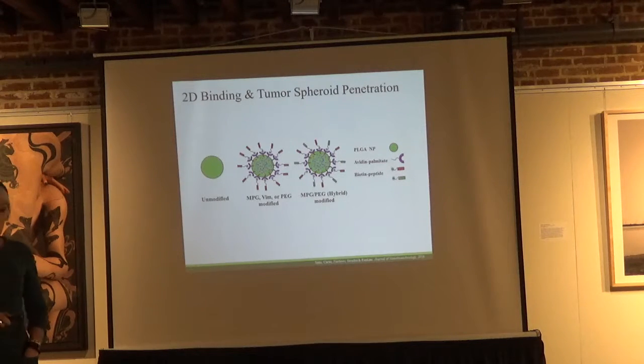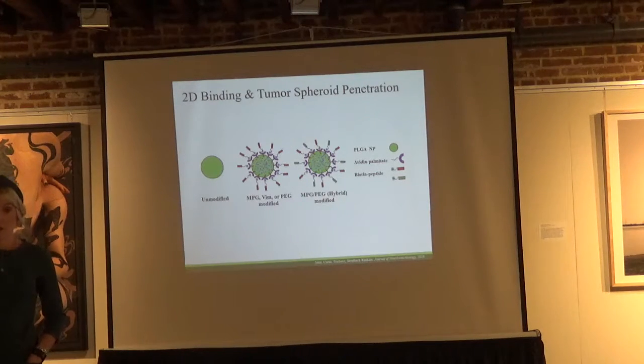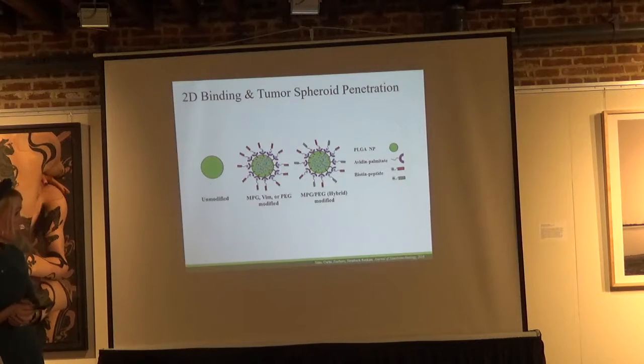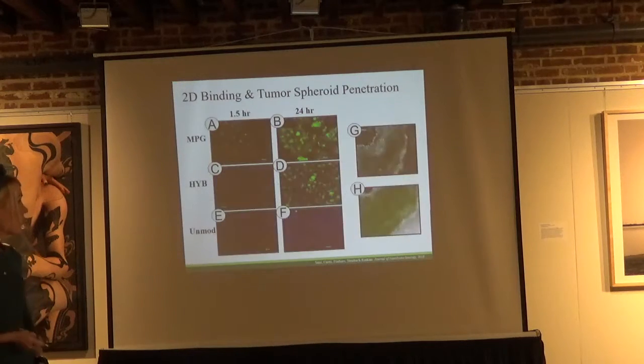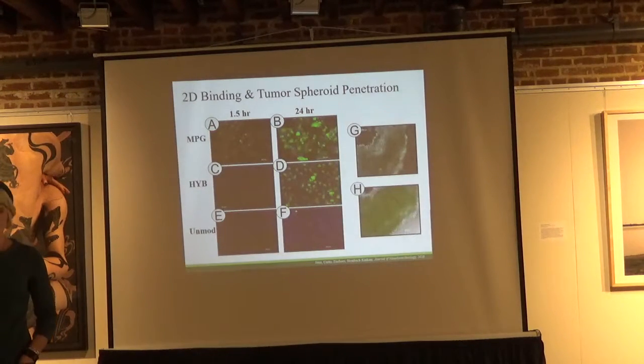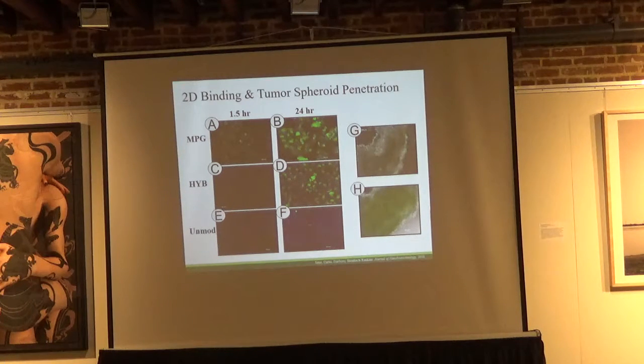And so using this particle platform as a basis with cell-penetrating peptides, we also looked at stealth modifications or co-modifications or co-treatments of different particle groups comprised of unmodified particles, particles coated with MPG, VIM, which was a tumor targeting marker, or PEG for stealth properties, and also formulated some particles that had hybrid modifications on the surface. And we wanted to look at how well they were not only taken up in 2D culture, because it's well known that while PEG, for instance, can provide stealth properties, they're also not internalized extremely well, and hence that's where we saw the cell-penetrating addition would provide more favorable internalization properties.